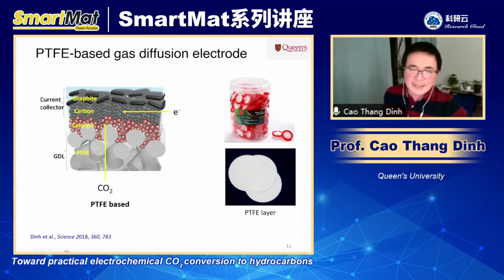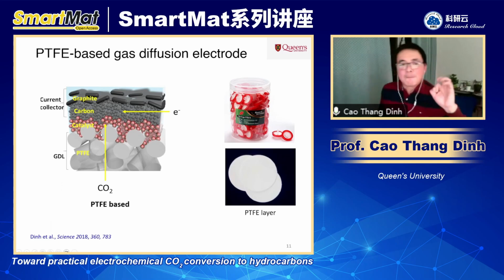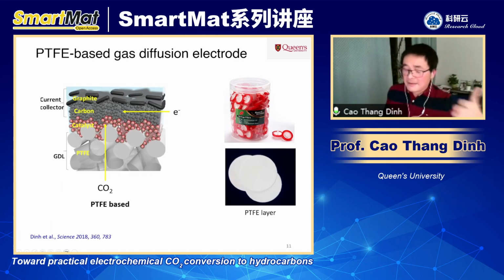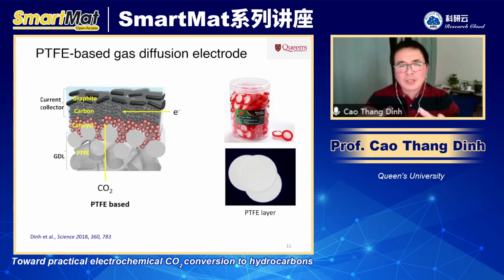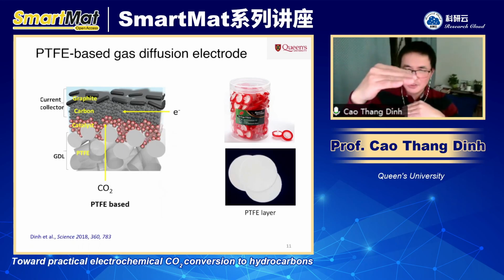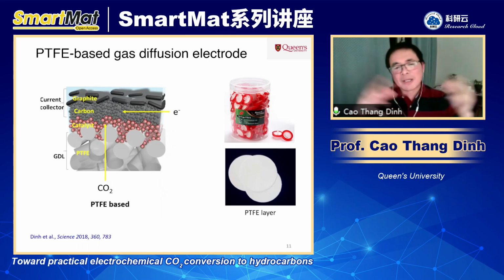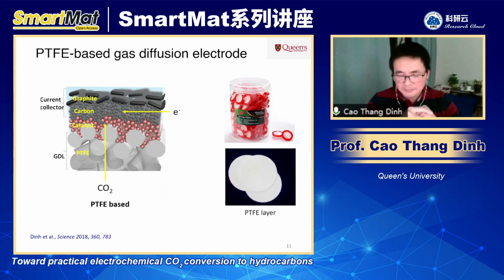So on the left-hand side here, you see a porous PTFE layer, and then we deposit the copper catalyst on top, still with the same physical deposition method. And then we add another carbon layer to increase the conductivity. Now you see, with the new configuration, we do not combine PTFE and carbon in a single layer, but we make them two separate layers with two different functions. This PTFE only allows the CO2 diffusion. We do not need the conductivity here, but we add the carbon on top to increase the conductivity. Now we decouple the functions of the two layers.